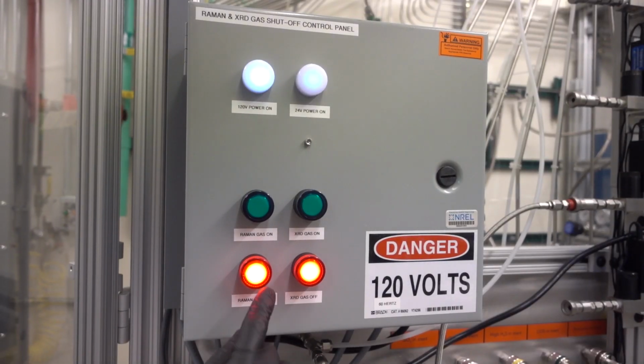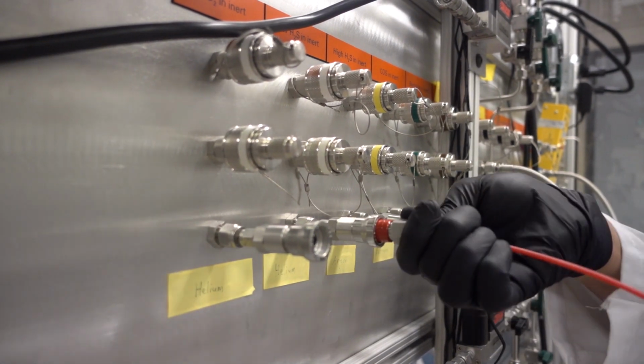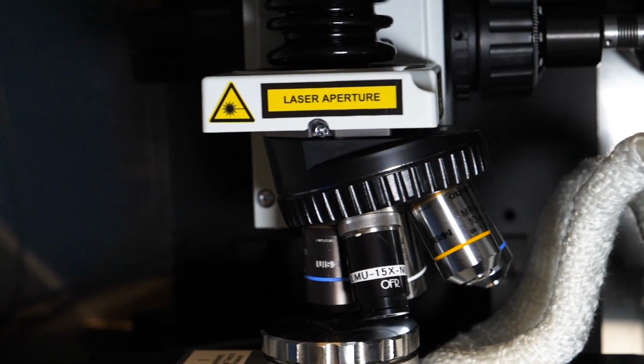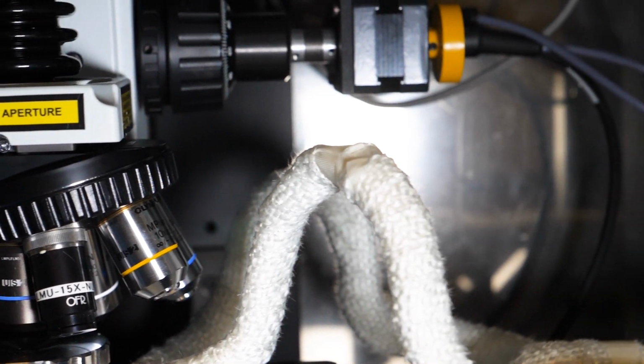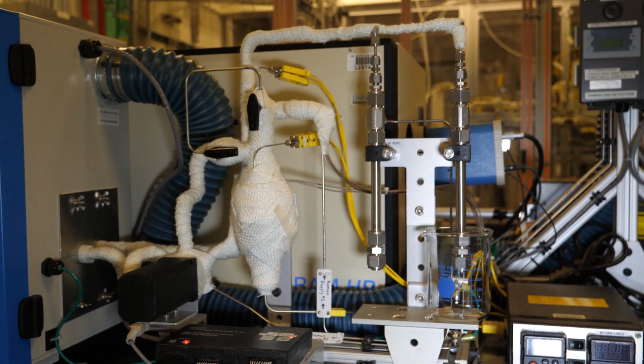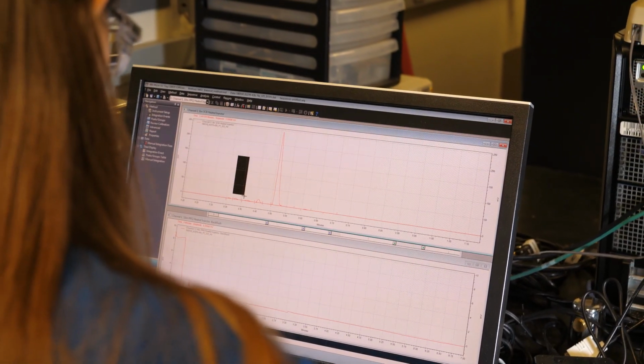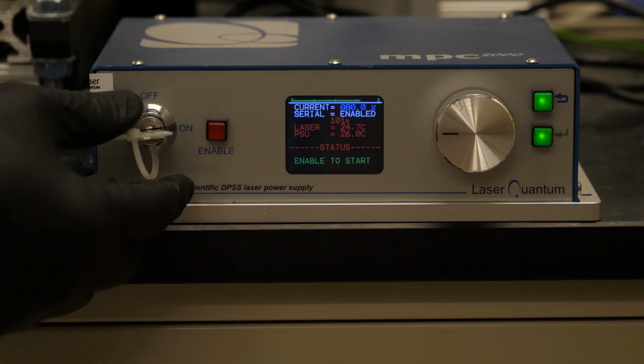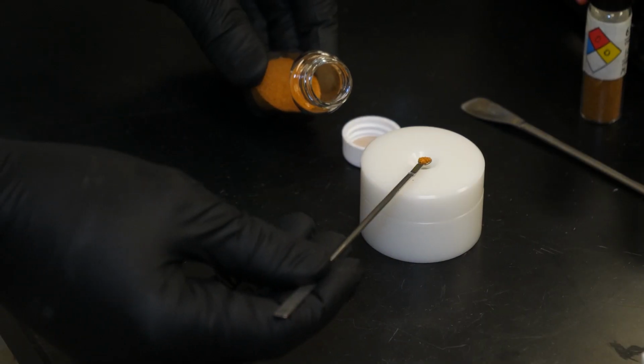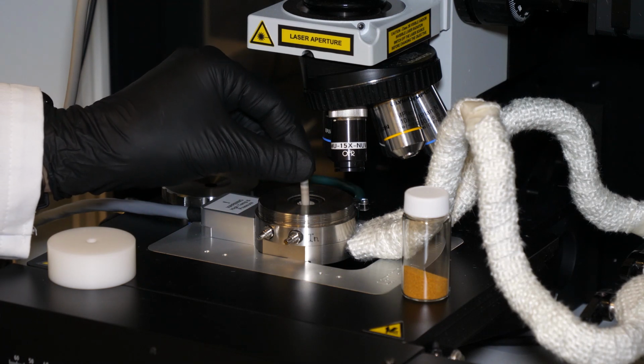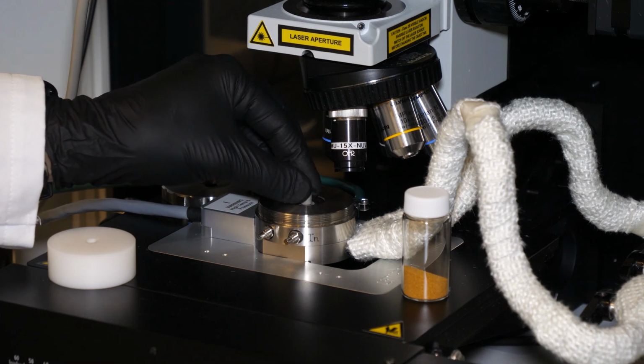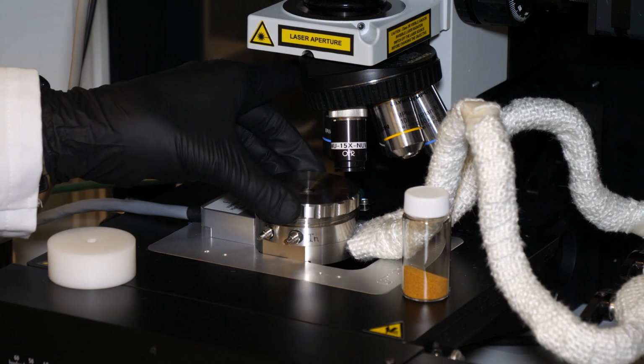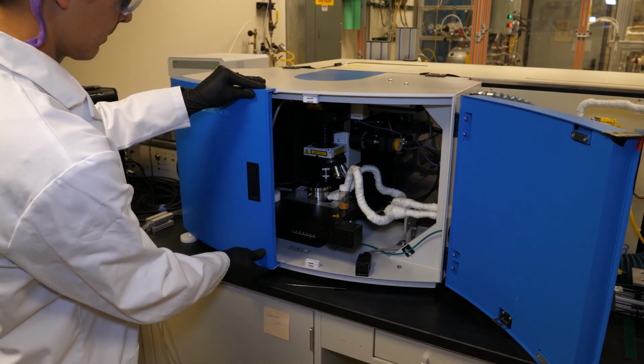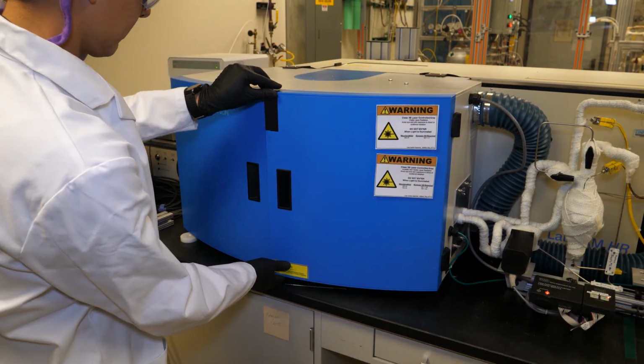undergoing chemical reactions. We're using operando laser Raman spectroscopy to study regeneration protocols for carbide catalysts. Operando laser Raman spectroscopy is a really cool technique that enables us to probe the catalysts during the reaction while we have a combination of gas chromatography and mass spectrometry to enable us to measure the catalyst's activity. This allows very good correlation between certain physical or molecular attributes of the catalyst and the activity of the catalyst for a chemical reaction, and to simultaneously see the formation of carbon species during the reaction and removal of carbon species during the regeneration. This allows us to select the proper operating temperatures and conditions to enable long-term activity of